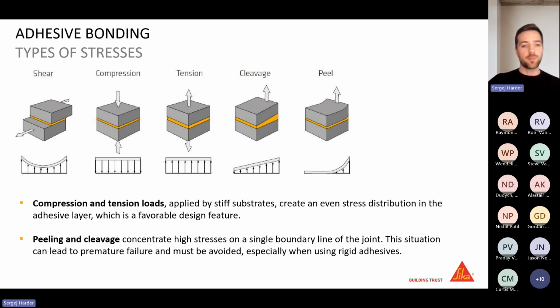What you have to prevent in most of your designs, or try to prevent, is this cleavage and peel forces. So for cleavage, we mean here an off-centric force acting on the adhesive with a quite stiff adherent. There you have also a non-homogeneous stress distribution, mostly acting on this part of the adhesive. And even worse, if you have a less stiff adherent, you have then peel forces, and then an even worse situation for the adhesive, because of course you created the surface for the adhesive to act, and now if you have an off-centering, very locally acting force, you take away this advantage or this acting surface for the adhesive, and now you reduce the load-bearing capacity of the joint.